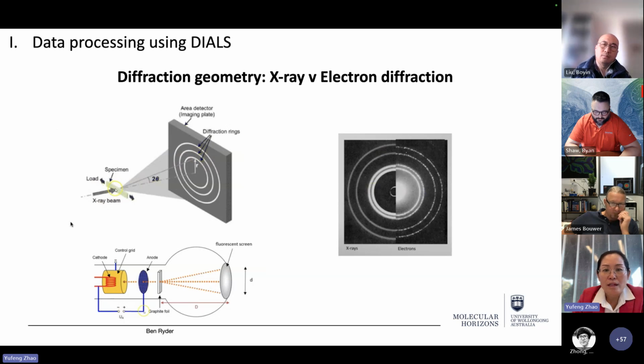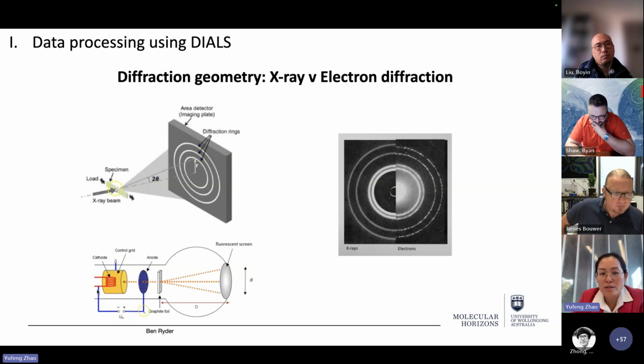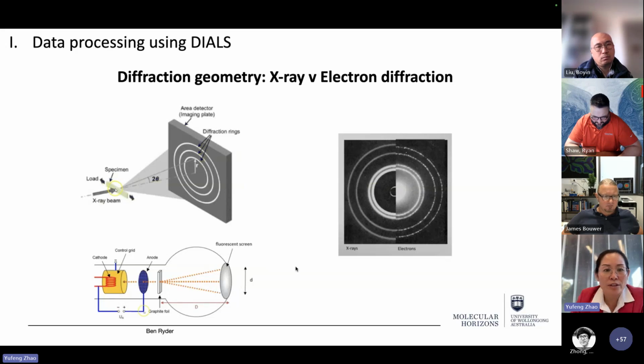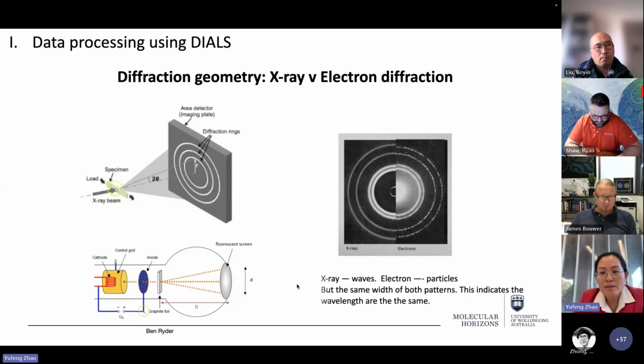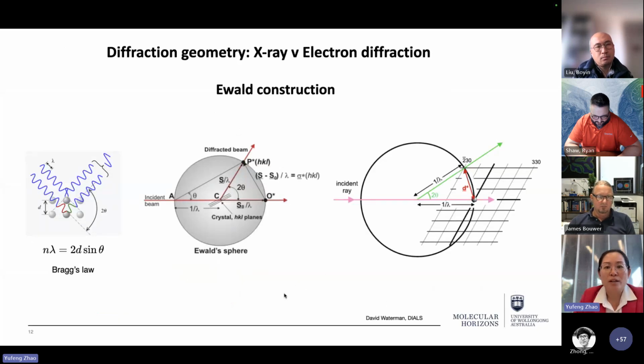Classic X-ray and electron diffraction are quite different. X-rays are more like waves, electrons are particles. But once electrons pass the diffracting part, they also generate wave-like properties, so in theory they are all diffraction. For X-ray, people care about this angle, where the beam intersects with the detector, and this is all based on Bragg's law. Here's the classic Ewald construction I want to mention a little bit. Bragg's law: lambda equals 2d sin theta, where lambda is the wavelength and d is the distance between the atom planes, related to the resolution.